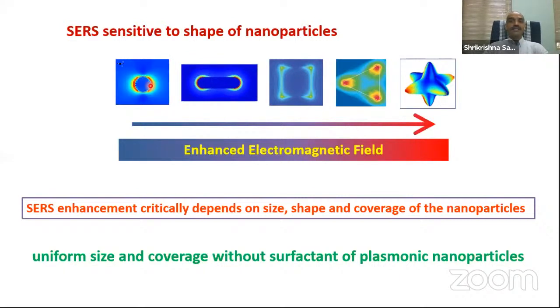If you can make these metal nanoparticles of different shapes, you can get different surface enhancement. But this enhancement will be restricted, for example, if I'm having this star shape, the enhancement will occur only at this edge. So if I put my probe molecule here, then I will not get the enhancement. But if I put the probe molecule at the edge, then I will get a huge enhancement. So I have to decide. For example, if I'm having nanorods, only at these edges will I get the enhancement. This entire region, from the surface enhanced Raman spectroscopy point of view, is not useful, because it doesn't give me any enhancement in the electric field. So there will be no enhancement in the Raman signal.